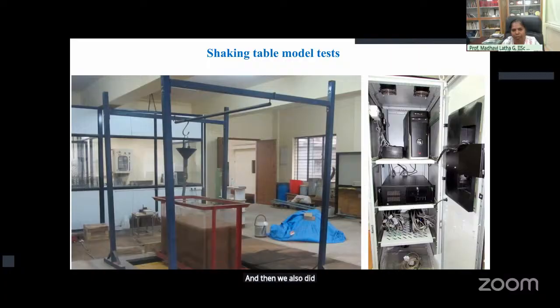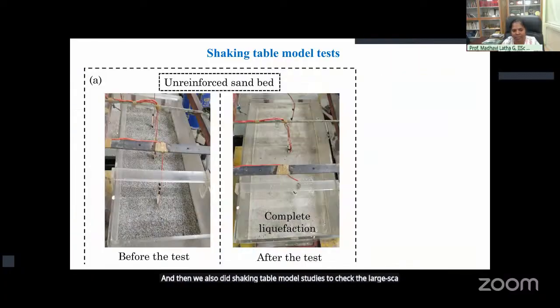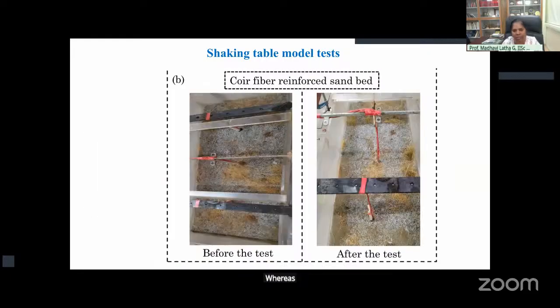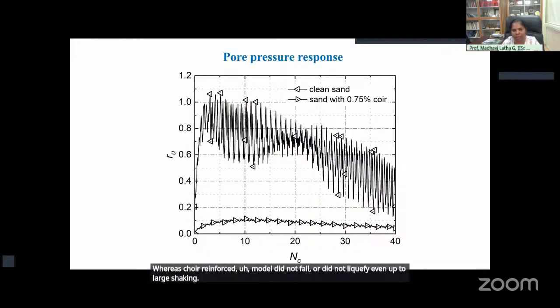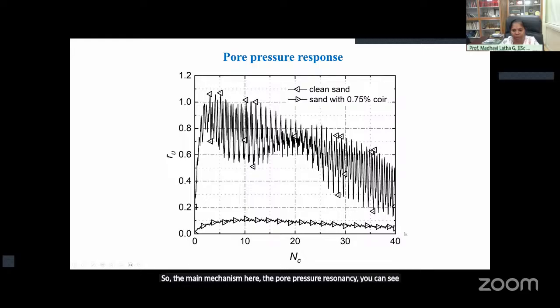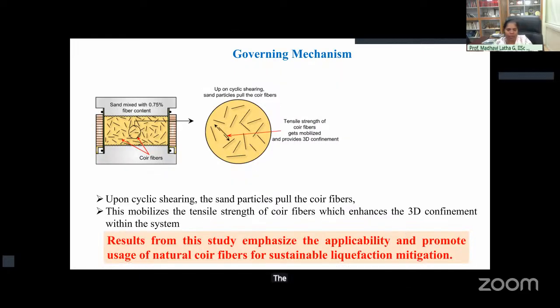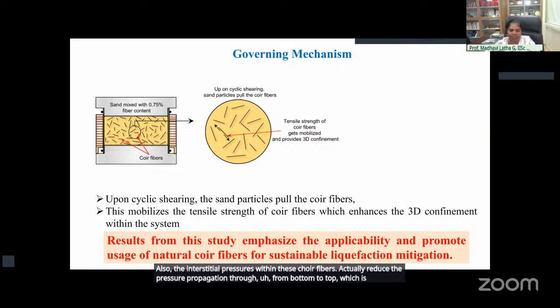And then we also did shaking table model studies to check the large scale applicability of this. And then we see that the unreinforced specimen failed quickly under shaking, whereas the coir reinforced model did not fail or did not liquefy even up to large shaking. So the main mechanism here, the pore pressure response, you can see that very, very low pore pressure response. The main reason is when you are applying shear, the coir fibers are getting stretched, and that provides additional tension, which opposes the movement of particles. Also, the interstitial pressures within these coir fibers actually reduce the pore pressure propagation from bottom to top, which is the main reason for liquefaction resistance.